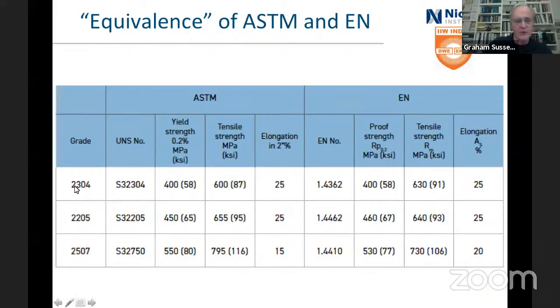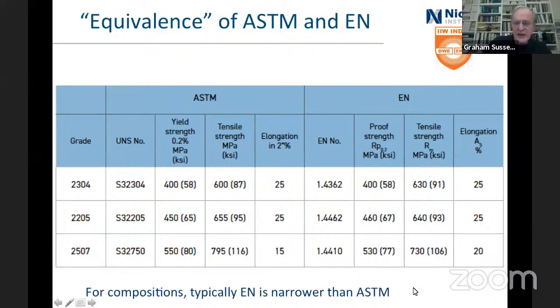And let's look at 3 different grades, the 2304, the ordinary duplex and the super duplex. So a lean duplex, and compare strengths. Yeah, not very different. And you really wouldn't expect it to be different. It's just the way these standards treat the materials. The tensile strength's about the same. Tensile strength of the 2507, again, about the same. Ductility, it's all in the 20 to 25, except for the ASTM version of the elongation in 2%. Sorry, this is elongation in 2 inches percent, and this is just the A5 arrangement. And for compositions, EN is typically a bit narrower than ASTM, although there's not a lot in it.